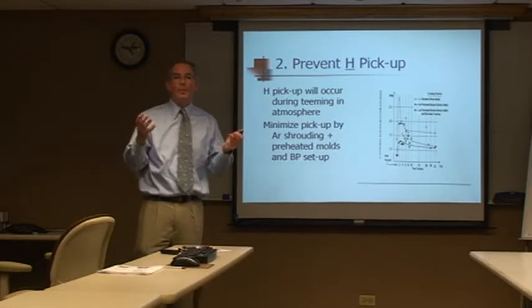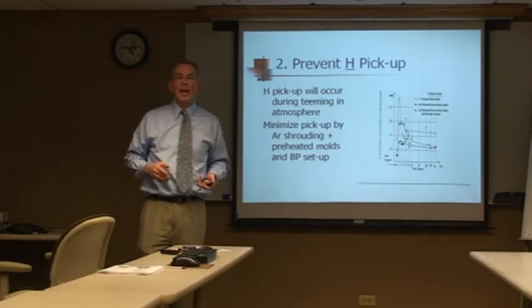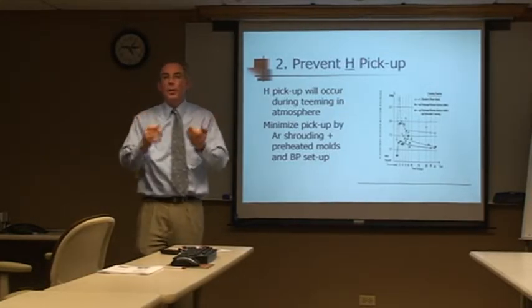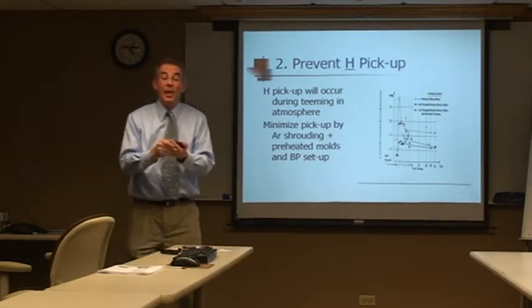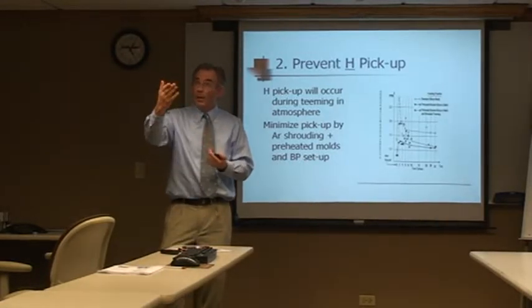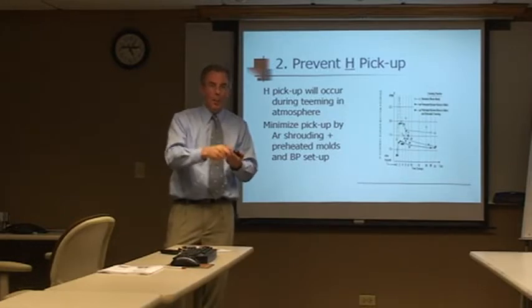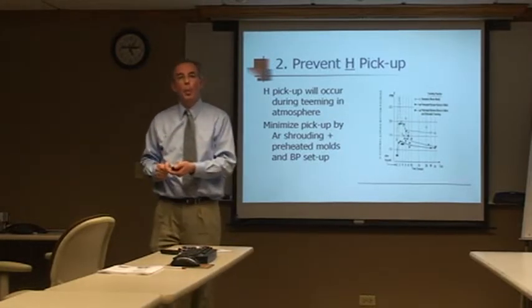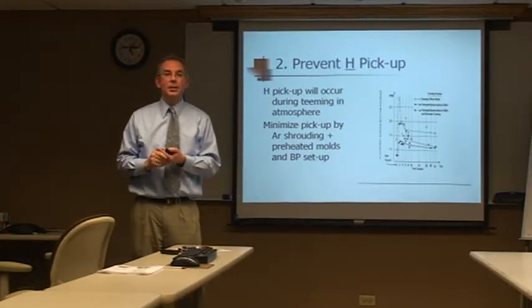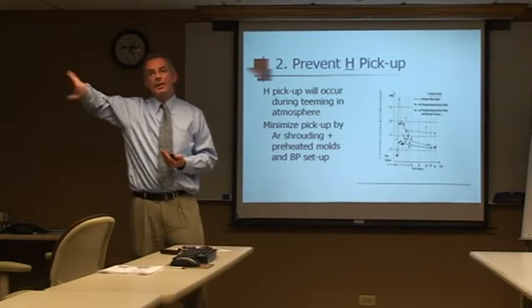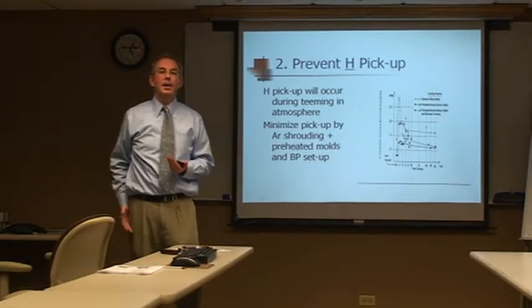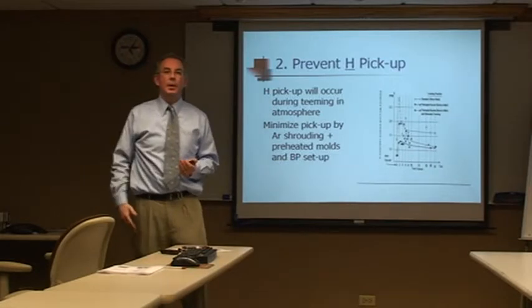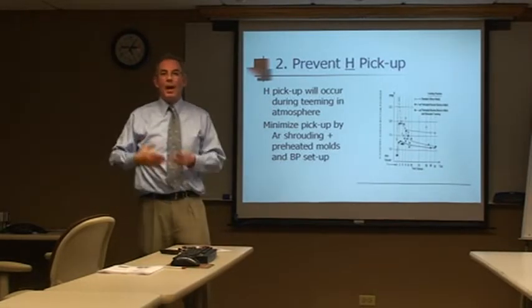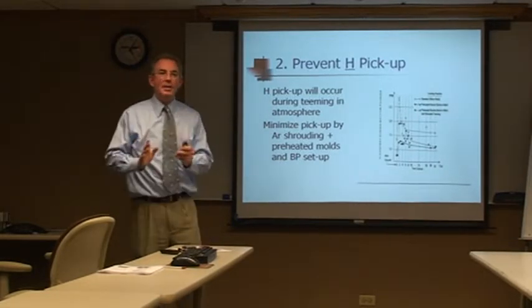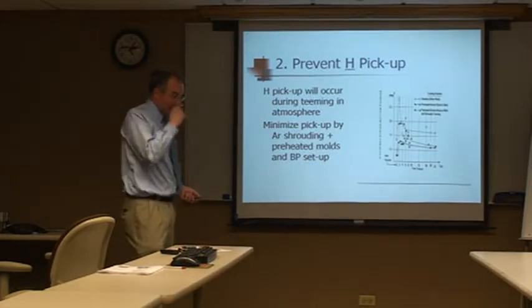All other elements, carbon, manganese, we'll average those together because, well, that's just the way it's done with ASTM. But with hydrogen, if we're working to our 2.0, and we have a 1.8, a 1.9, and a 2.1, that heat's certified as a 2.1, even if it means that heat is non-conforming and has to be dispositioned in another manner rather than going to the customer. Always erring on the side of caution with hydrogen.